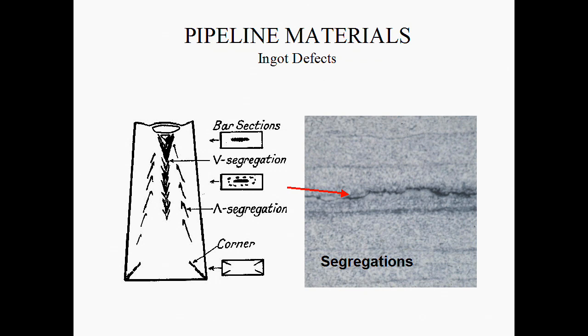But if they're very small, and if you don't hold at temperature for a very long time, they're trapped within the metal and they're just pushed ahead on the solidification front. So as it's solidifying, these little particles stay at the interface between the liquid and the solid, and they get moved in towards the middle. Eventually they get surrounded by metal, and then you get these segregation patterns.